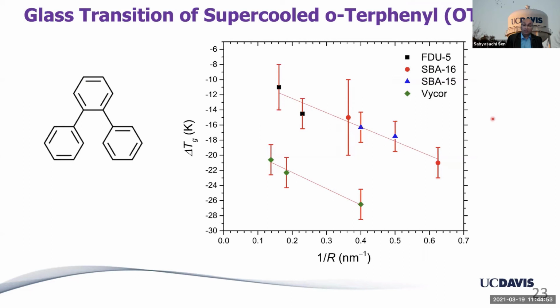And now I want to finish the talk, if I can get 5 more minutes, on glass transition of another molecular liquid, this time much simpler than glycerol in the sense that this is a van der Waals bonded liquid, no hydrogen bonding. This is orthoterphenyl, OTP as it is lovingly known in the glass community, at least. So we put OTP in all these nanopores in mesoporous silica, and we saw that the TG actually drops with size, and the TG drop follows a Gibbs-Thomson type linear relationship, delta TG like delta TM.